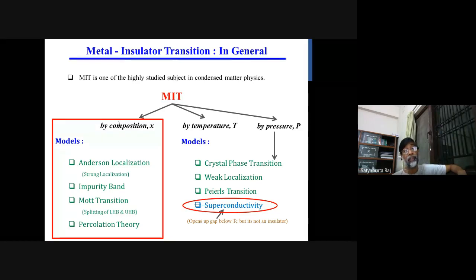Whereas if the doping generates a strong Coulomb interaction, then it can also lead to a Mott transition with a satisfied Mott criterion, and it splits the conduction band into a filled lower Hubbard band and a fully empty upper Hubbard band, and this can explain an MIT. Also percolation theory can explain an MIT. This happens when you change the composition X. Whereas if you change the temperature, then also you can achieve this MIT.